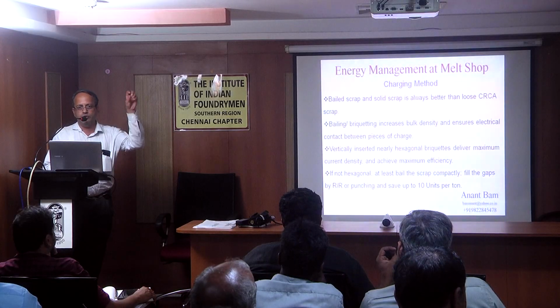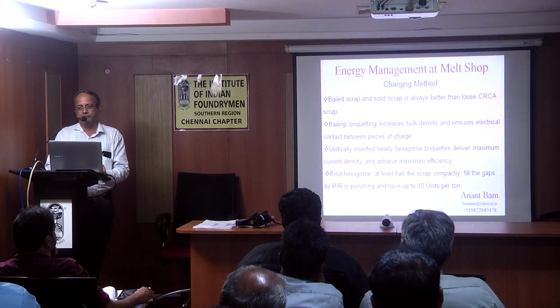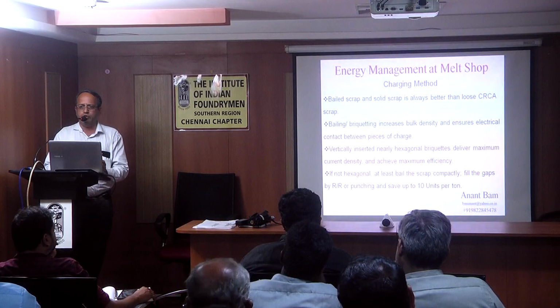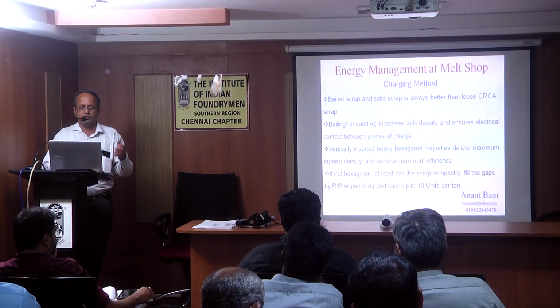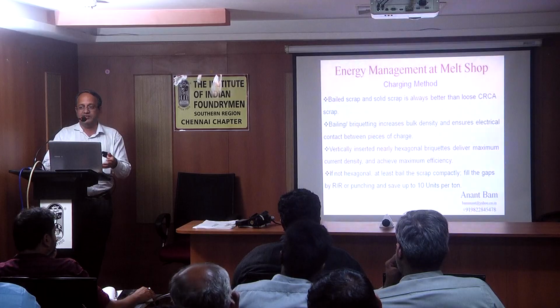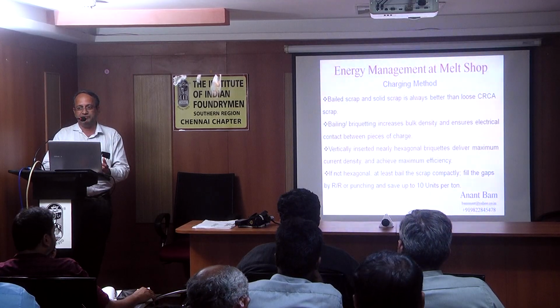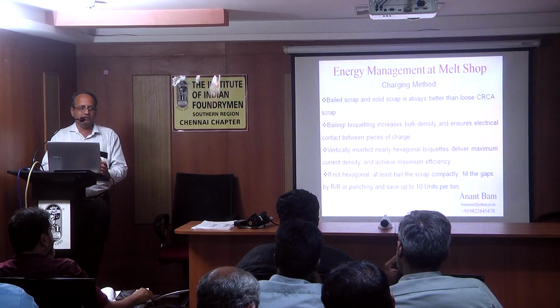So if you are charging loose scrap instead of bale scrap, you are consuming more energy. You are not allowing that energy to penetrate the iron because there is no iron. There is air in between. So pack it densely.